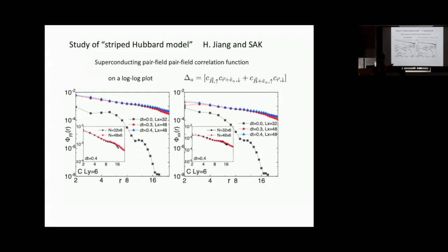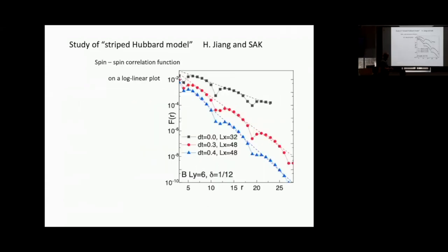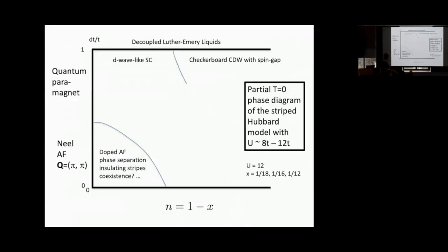And this correlation is falling like a power law with distance. This is the y-directed bonds. This is the x-directed bonds. So this really is a D-wave superconductor, D-wave-like. Again, the exponent that we get for the fall off of these is something around 1. This is the spin correlations, which fall exponentially with distance, with actually rather short correlation lengths. So presumably, there's again this region of doped antiferromagnet that I'm not prepared to say much about, but what we found is that there is a region here which corresponds to a doped quantum paramagnet in which we find D-wave-like superconductivity.